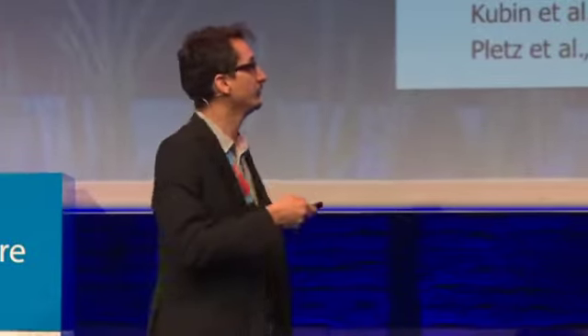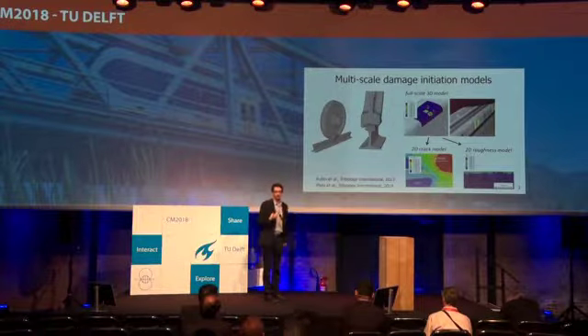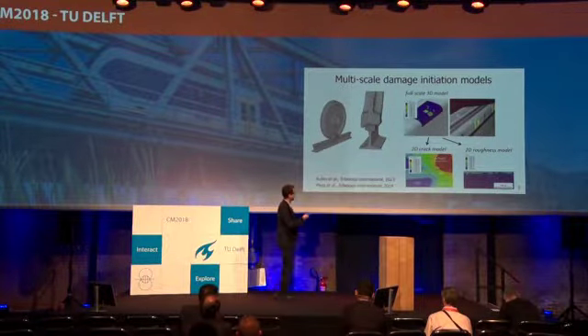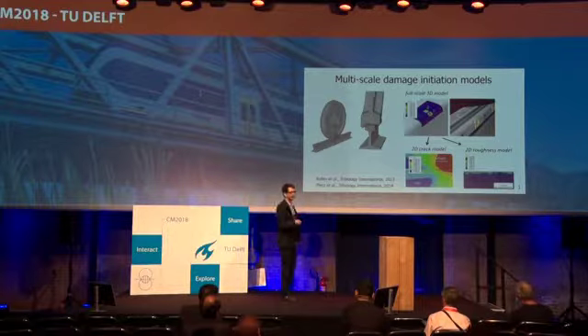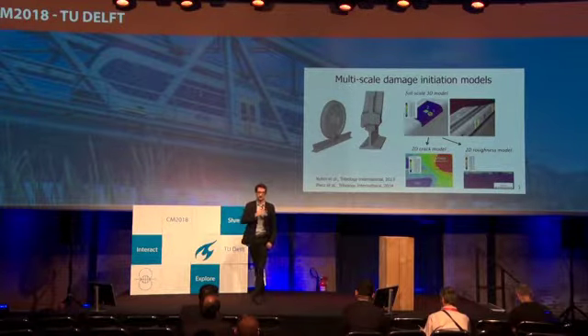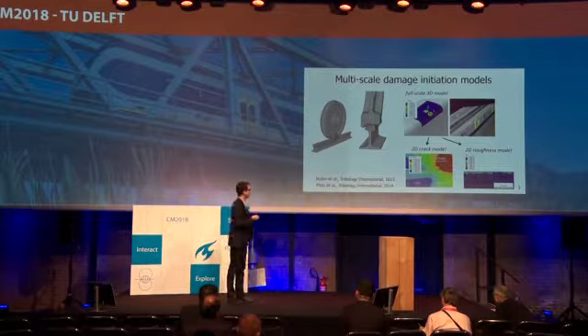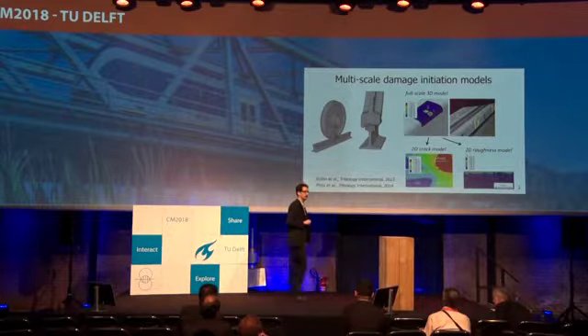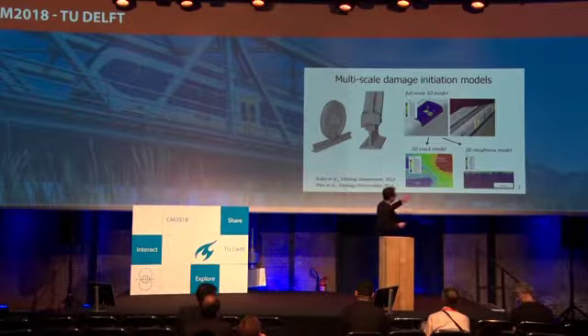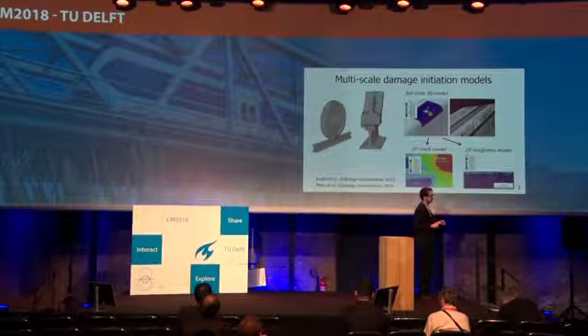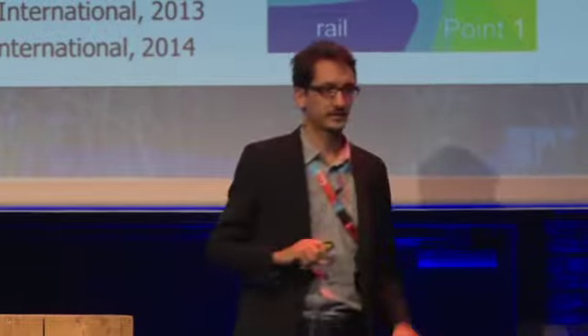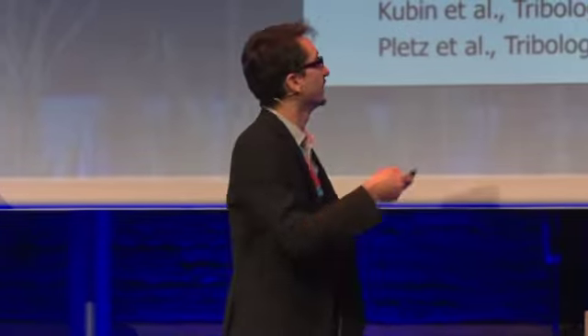And then we went into 2D models, one with a crack, where we try to investigate what happens to the crack, what differences on that scale, or what parameters on that scale influence the crack driving force. And we also used a roughness model, where we saw that the small asperities and roughnesses influence the upper surface layers, some micrometers. The plastic deformation is highly influenced by this roughness. And basically, we thought about how to transfer loads from 3D to 2D. 2D is really good because you can use roughness and cracks very efficiently.